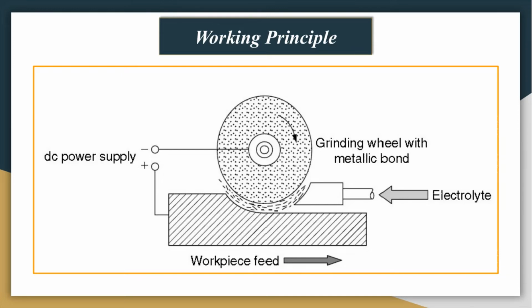The insulating abrasive material, that is diamond or aluminum oxide of the grinding wheel, we have to set in a conductive bonding material. In this technique, the non-conductive abrasive particles act as a spacer between the wheel conductive bond and the anodic workpiece. Depending on the grain size of these particles, a constant inter-electrode gap, that is IEG, of 0.25 mm or less can be maintained, through which the electrolyte is flushed. So we have to flush out the electrolyte in between that gap.